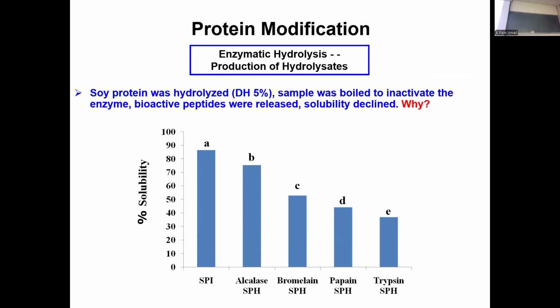So, what do we do usually in the lab when we use enzyme after enzymatic hydrolysis? We have to denature the enzyme, otherwise it keeps chopping on the protein. So apply thermal treatment. Even if we hydrolyze and then apply thermal treatment, you're still going to get aggregation when you heat treat. Those peptides are not too small. We don't usually hydrolyze more than 8% degree of hydrolysis, but with the heat, you are really inducing polymerization through hydrophobic interaction. So it didn't work in this case.